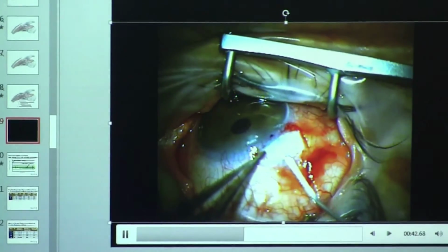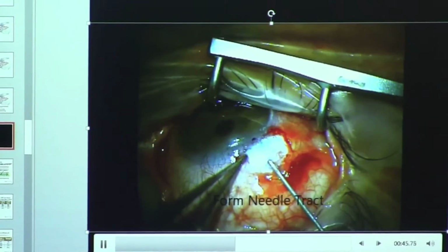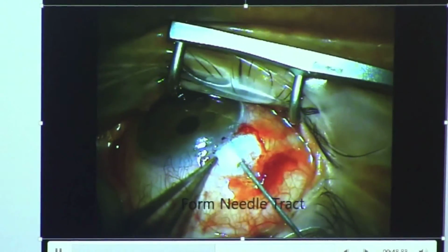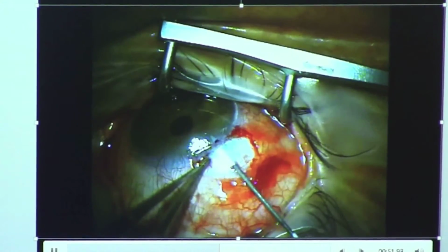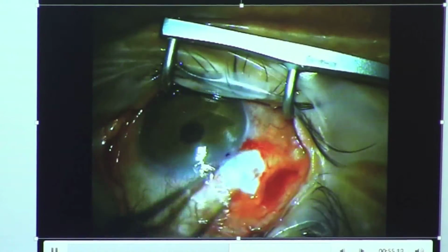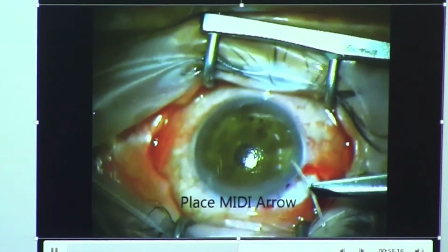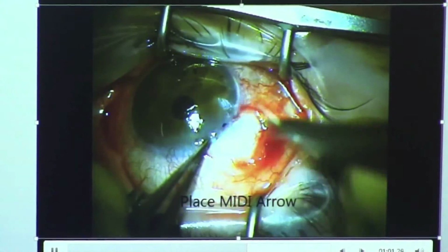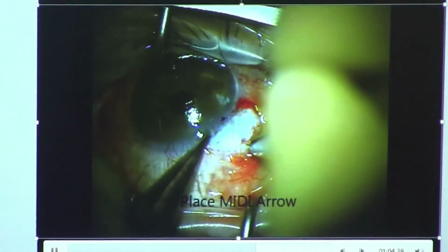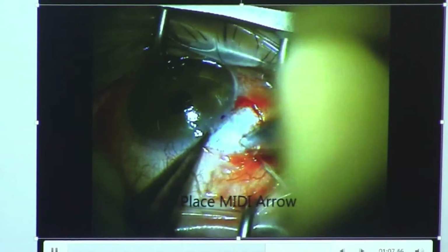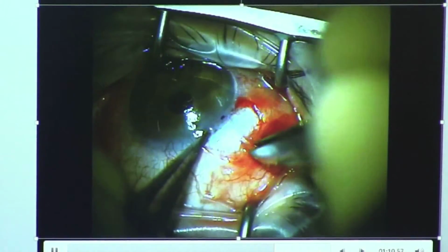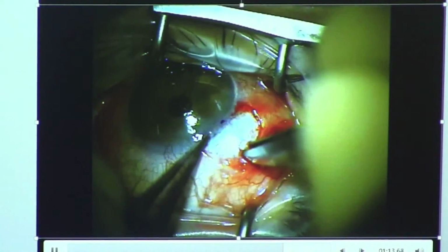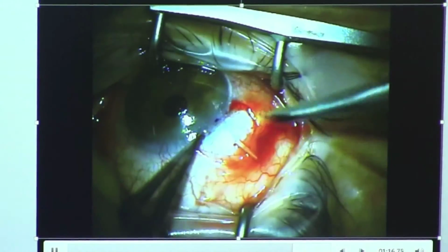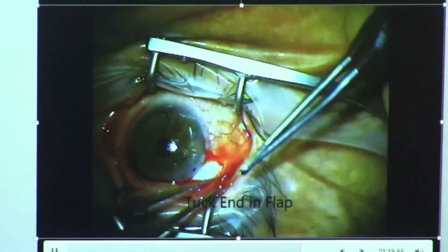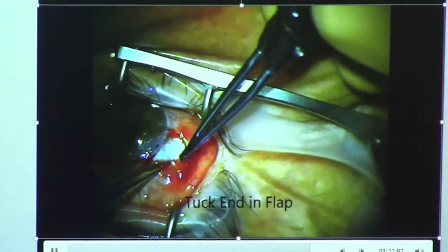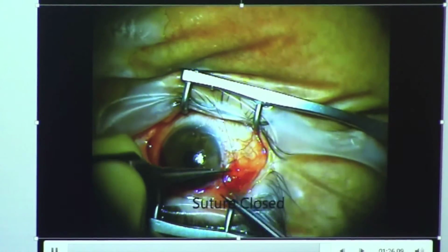And now she just changes magnification, so you have to bear with me here. Put a needle tract in, that is a 25 gauge needle. And it goes into the anterior chamber. And we can't put it in with an inserter because the fins are too big. So you take the device just with a forceps, and it's pushed through this needle tract. And the fins are pushed in, and they serve like a cork on a bottle. It keeps fluid from coming around it, and it keeps it from migrating in any direction. She'll check it for flow, and she'll put it underneath the conjunctiva and just put a couple of sutures on it to close the conjunctiva.